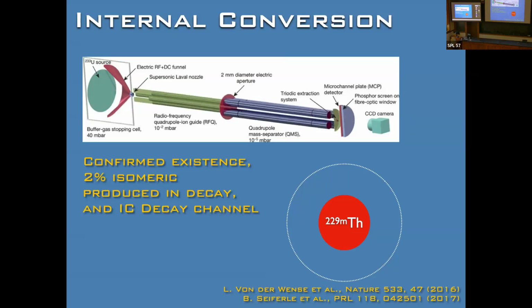And that was partially in response to some beautiful work that came from Peter Thirolf's group at LMU in Munich. Peter did a really cool experiment where he had uranium-233. When this alpha decays, it produces thorium-229. And 2% of the time, that thorium is in this nuclear excited state that we're looking for. And so he then guided that through a quadrupole so that he could only get exactly thorium-229. And then he would soft land it on an MCP detector.